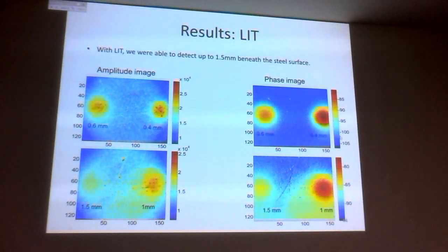So before you apply the truncation of the correlation function, until this new title, the axial resolution was determined by the chirp, wasn't it? This is a lock-in thermography, so it's depth average. But the repetition time of the chirp determines essentially how deep you're going to see. The frequency content of the chirp also is going to determine your spatial resolution, because high frequencies delineate boundaries better. The actual resolution depends essentially on the decay time of the thermal profile.